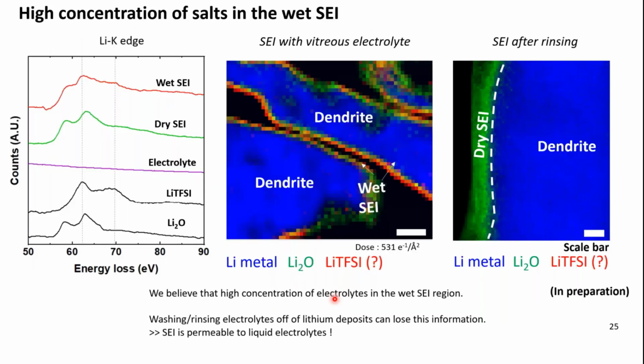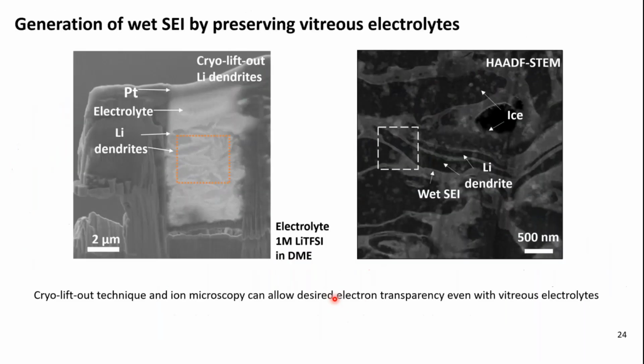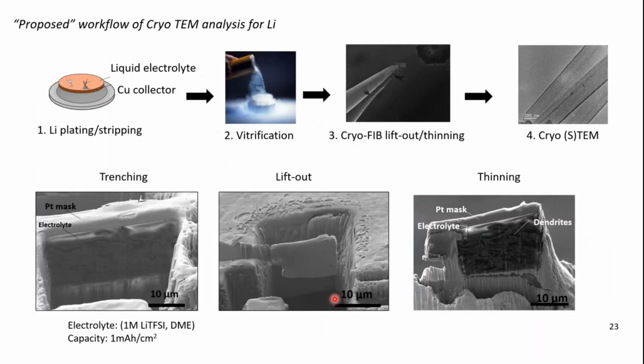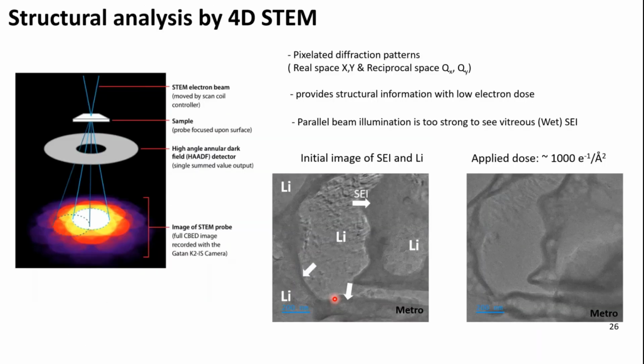the imaging of wet SEI, I realized that it is really difficult to get high resolution imaging because the electrolyte and wet SEI are very beam sensitive. So even if my dose rate is 10 electrons per angstrom squared per second, while I navigate or locate my sample it will damage very easily. So yep, that's all.